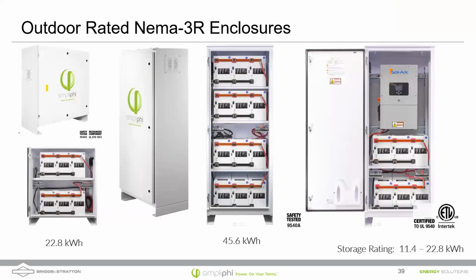And Nathan, we did have a question about, are there any ambient temperature restrictions on our batteries? So yes, we do. On the standard Phi battery, the AmpliPHI and the SimpliPhi, we can discharge down to -20 centigrade up to 60 degrees centigrade. Now on the charging side, we're more limited on the Phi battery. We can go down to 0 degrees centigrade up to 50 degrees centigrade for charging the Phi.